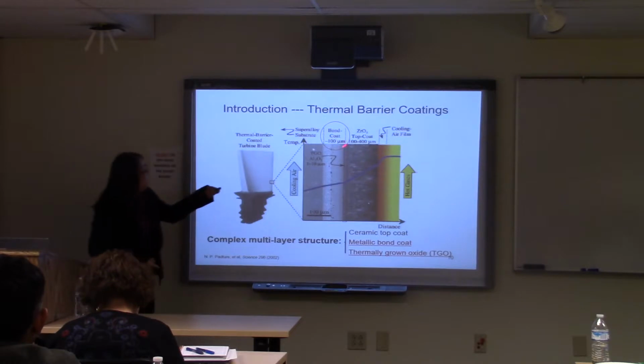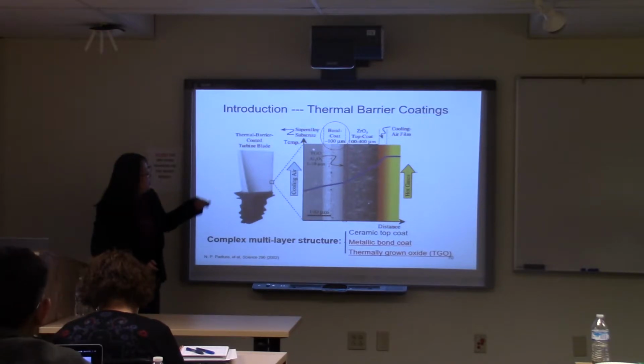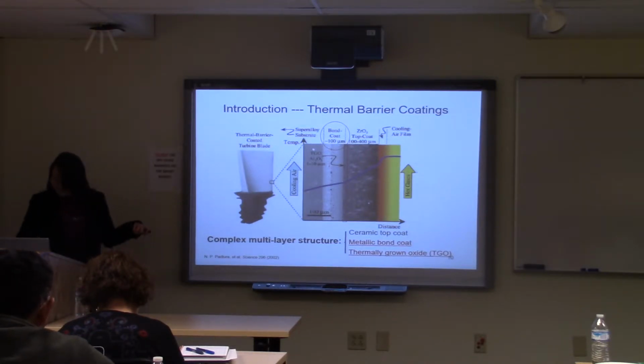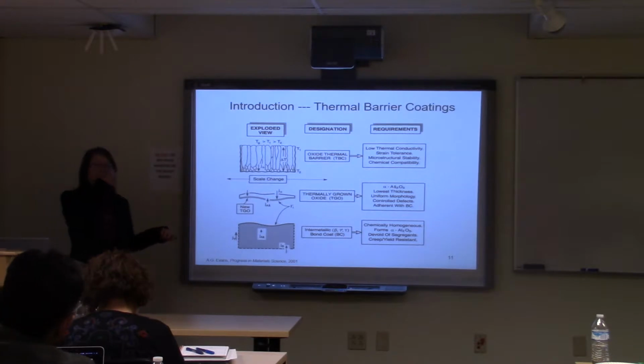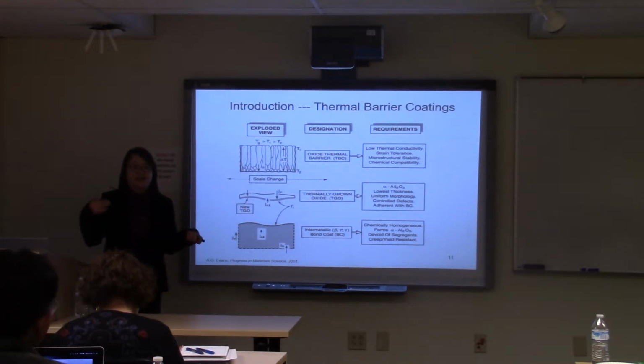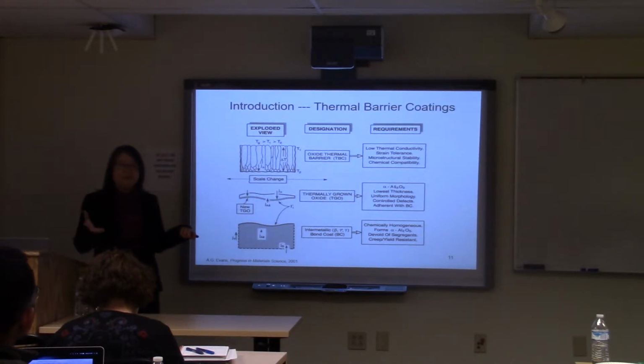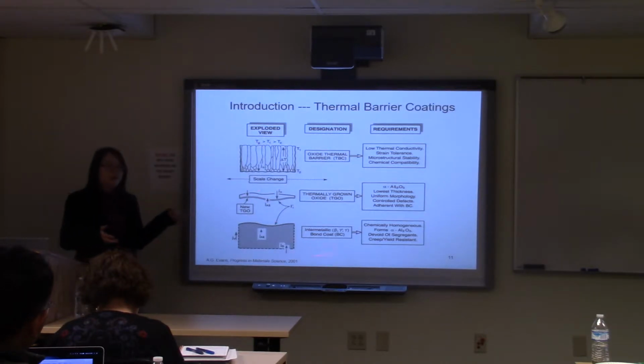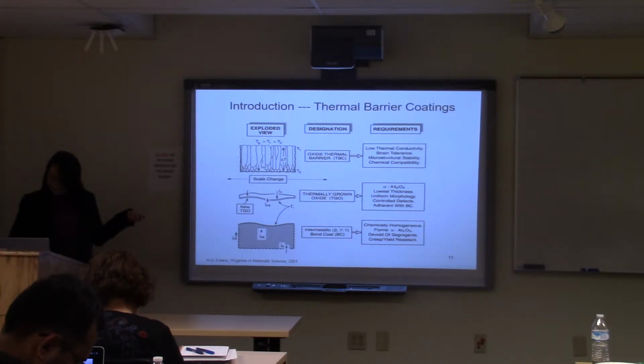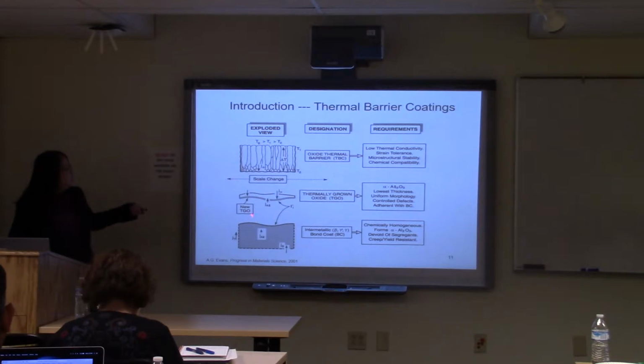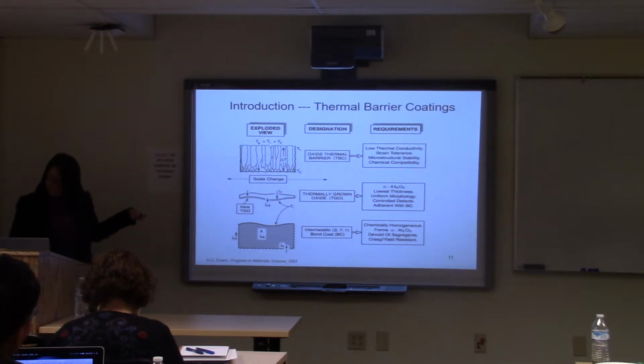In between, we also find an oxide layer forming between the top coat and the bond coat. It's very important to be aware that this oxide is not a layer we put in on purpose at the beginning. It's a reaction product during the operation of the thermal barrier coatings, due to the diffusion of aluminum to this interface and the penetration of oxygen.